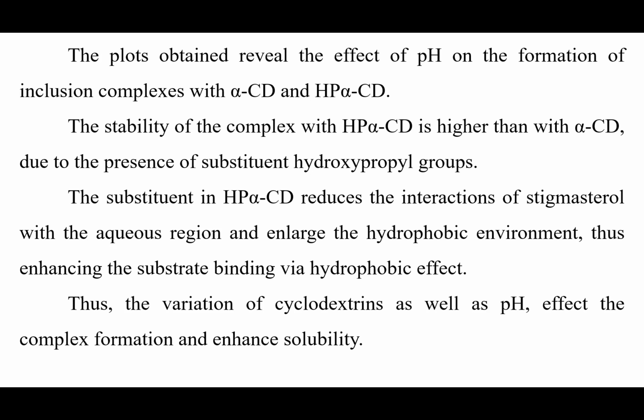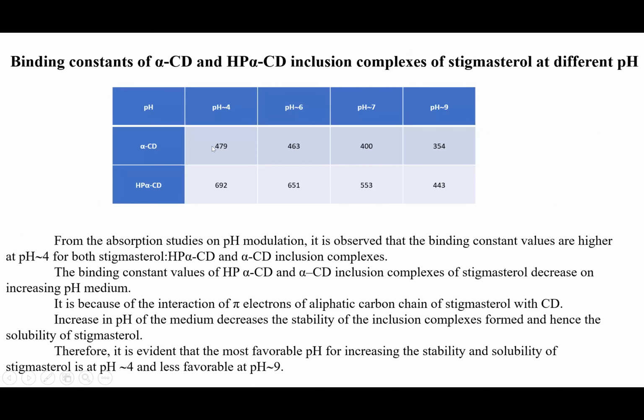Usually these inclusion complexes have very little binding force. So here in my case, from other studies like NMR and computational studies, I have arrived at the result that of the two ends of stigmasterol, only one end is getting into the wider rim, the wider cavity of alpha CD. So the variation of cyclodextrin as well as pH also influences the complex formation, thereby enhancing the solubility of stigmasterol. So these are the binding constants.